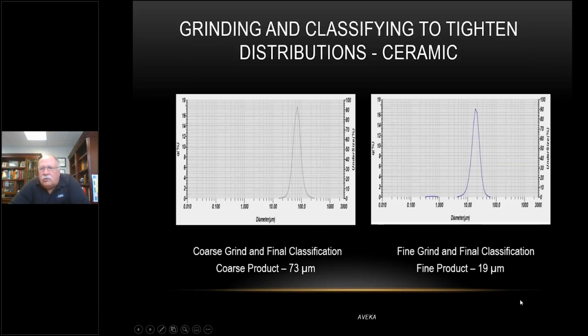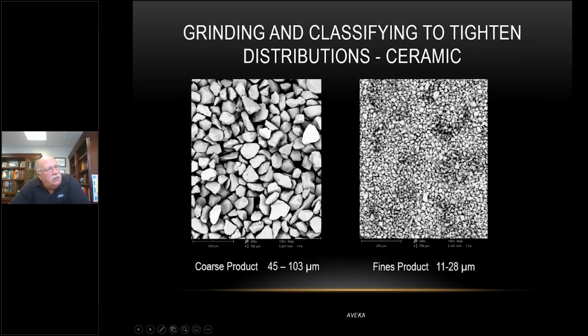Just to show you what this looks like from an SEM, remember all the fines that were in the coarse product and the fine product, and they're all gone. This is a nice tight distribution for an abrasive application. Really worked out nicely. And this once again is a classic jet milling air classification two-step process to get this type of tight distribution.